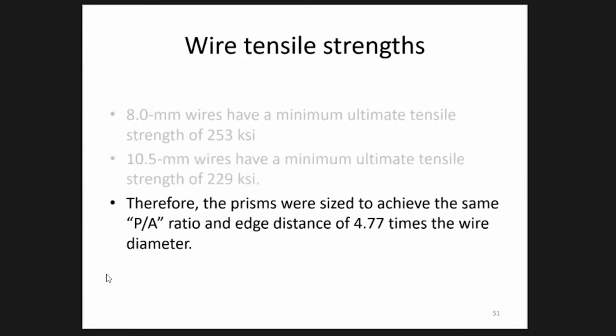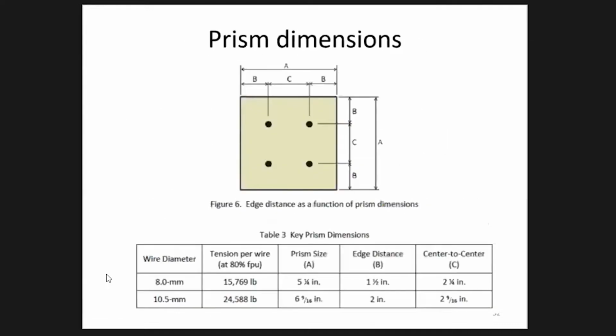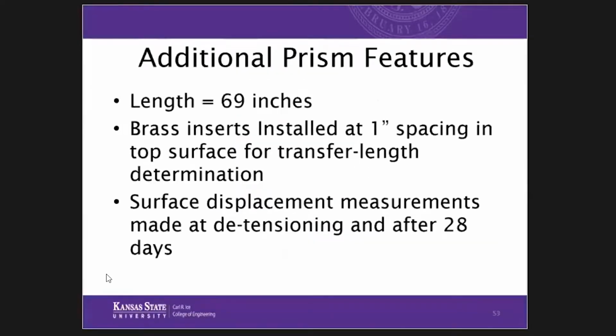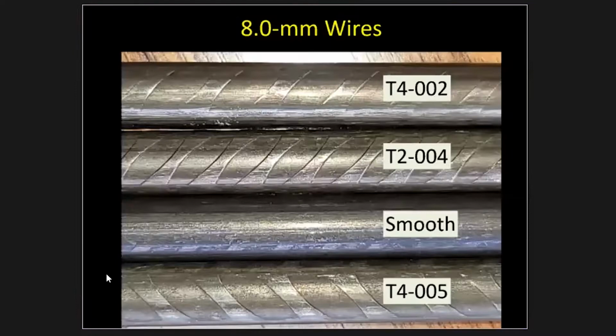So by keeping the edge distance at 4.77 times the diameter, we came up with the following prism sizes. For the 8 millimeter wires, the wires were tensioned to 15,769 pounds. They were 5.25 inches square with the 1.5 inch edge distance. And for the 10.5 millimeter wires, each wire was tensioned to about 25,000 pounds. There were 6 9/16 by 6 9/16 with a 2 inch edge distance. Additionally, they were 69 inches long, and we installed brass inserts to be able to determine surface strains and transfer lengths.